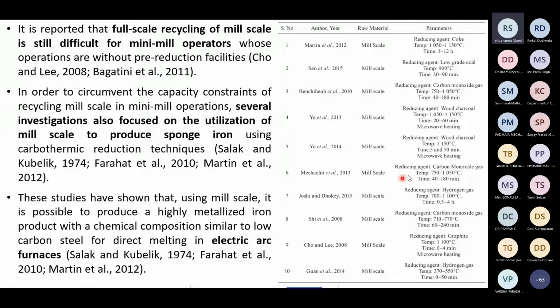It is reported that full-scale recycling of the mill scale is still difficult for mini-mill operators whose operations are without pre-reduction facilities. The mill scale contains nearly 40% to 50% iron oxide, and the remaining is different kinds of oxides of various metals. So it cannot be directly utilized. We need to reduce it. When we try to reduce it, the small scale industrial operators fail to do that because they do not have pre-reduction facilities.